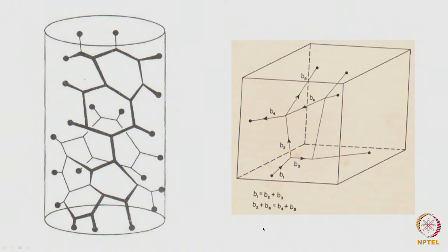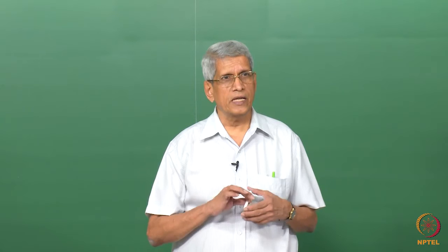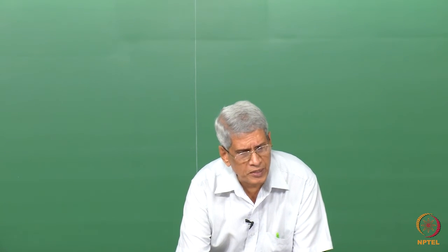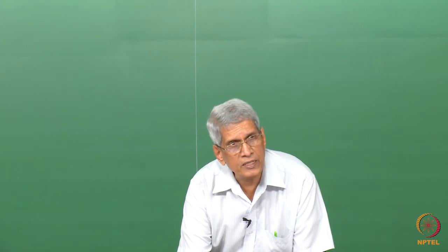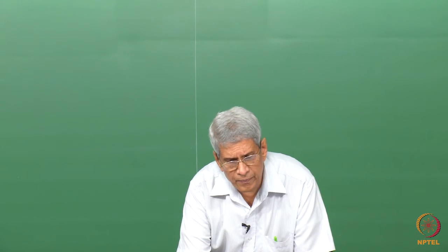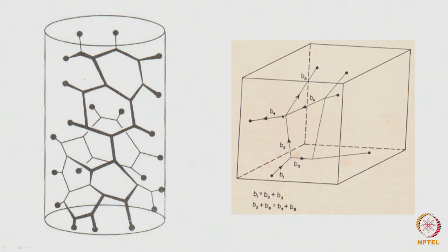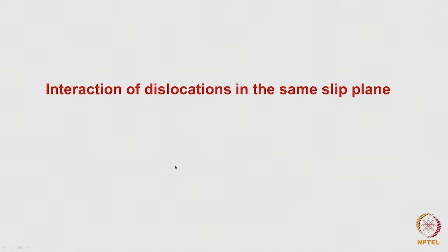Okay. We have studied another property of the dislocation, that when the dislocation forms in the material, it cannot end within the material. That means that the dislocations should be interconnected. That is what is being shown in this picture, that the dislocations are interconnected and the dislocation ends can come out of the sample surface at many points. And another important property which we have studied is that as dislocations come and join at any junction, the sum of all the Burgers vectors around that point has to be equal to 0.